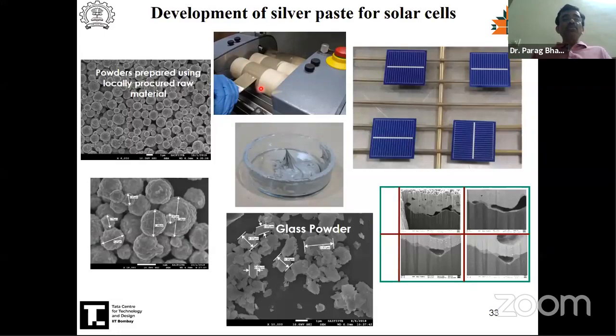So we put all these materials together. The glass powder, as I said, we make it ourselves. We melt the glass, we cast the glass, and we make powder out of it. We make these silver powders. Okay. And after high shear mixing, we make this paste. And this paste has to have very special flow behavior. And then we take this paste and we use something called a screen printer. And this is what is printed here in IIT Bombay on wafers to make the solar cells. And then we do characterization.